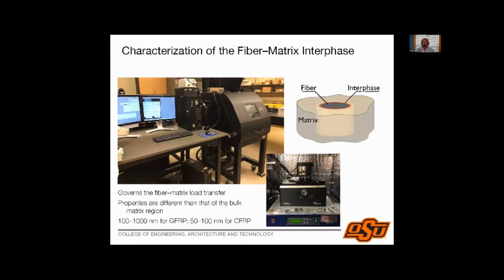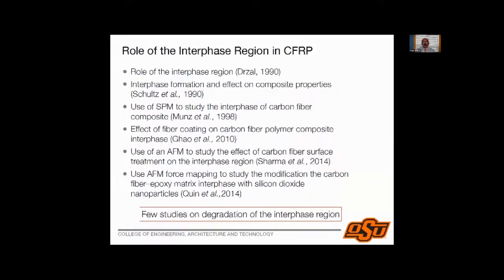So this is an atomic force microscope that we have in the lab. The actual microscope is inside this box over here. And even inside the box, you will see that there's a lot of vibration isolation and positioning systems, and the AFM is over here. If you're familiar with AFMs, then you will know this, but if you're not, they work on a very simple principle. There's a cantilever beam, and at the tip of the cantilever beam, there's a micro machined silicon tip, and the tip basically interacts with the surface. And the way AFMs are typically used is you try and map the topography of the surface. You can map the topography of the surface, you can map the chemical characteristics of the surface. What we want to do is we want to take this tip and we want to drive it into the material and carry out an indentation experiment at the length scale of an AFM tip. And if we can do that, then we can analyze the indentation data to get the properties.